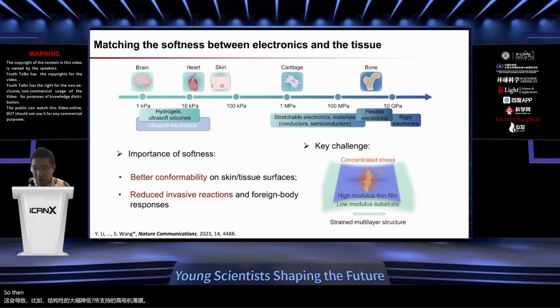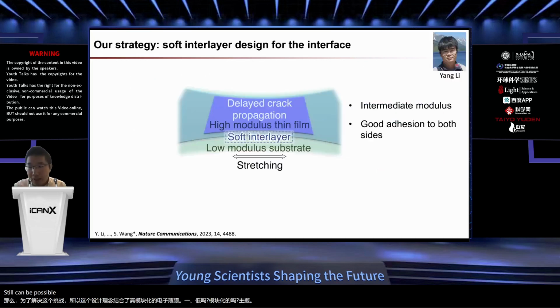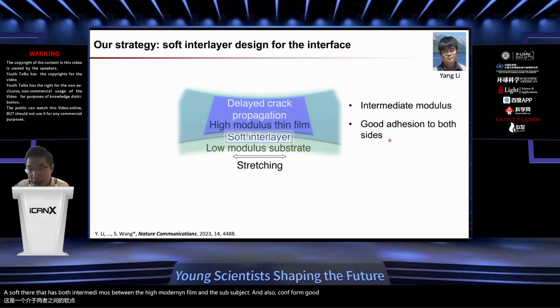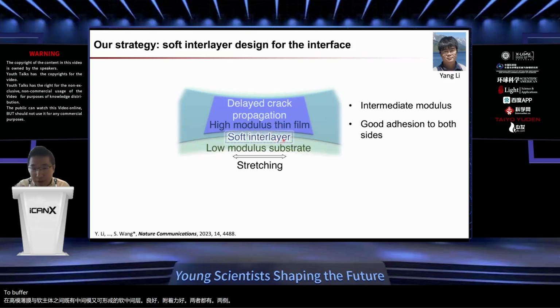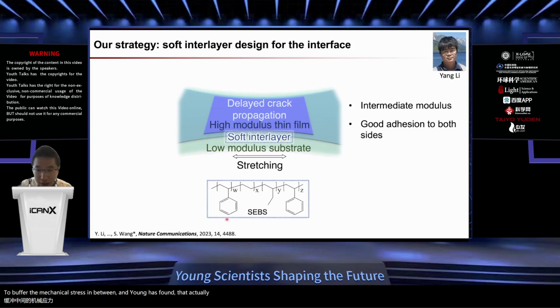So to address this challenge, so that this general design idea of combining high modulus electronic films with a low modulus substrate can still be possible, my student Yang Li came up with an idea, very simple but with universal applicability: inserting a soft interlayer that has an intermediate modulus between the high modulus thin film and the soft substrate, and also can form good adhesion to both sides to buffer the mechanical stress in between. And Yang found that a very commonly used elastomer, so-called SEBS, can do this function very well.